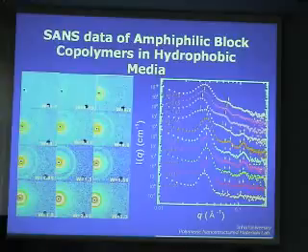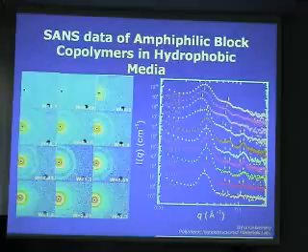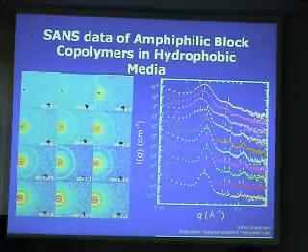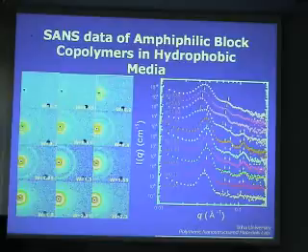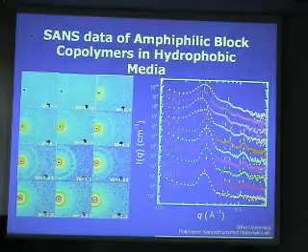This peak position can be indexed by the two-dimensional hexagonal lattice, indicating that this material is a hexagonal columnar structure. And above 1.55, we have a cubic phase structure. And at W equal to 1.55, we have a bimodal behavior of the hexagonal phase and the spherical phase together.